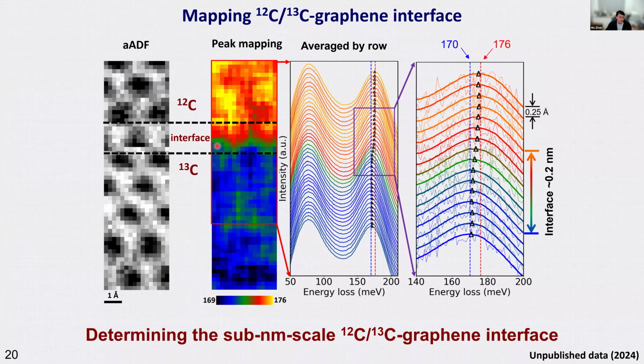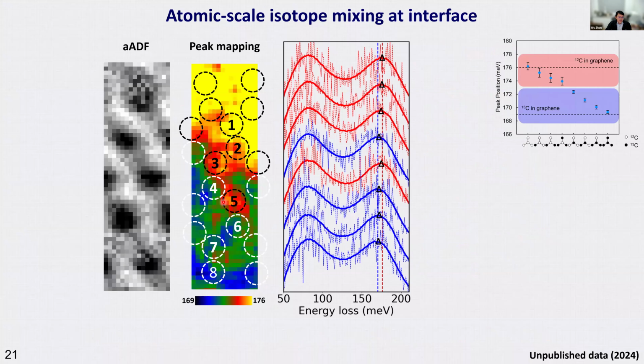And we see a switch just across this carbon-carbon bond. So we have a spatial resolution better than 0.2 nanometer here. And we can go one step further to look at some area where we start to have isotope mixing, and we can identify that here we have a carbon-12 in the carbon-13 part.